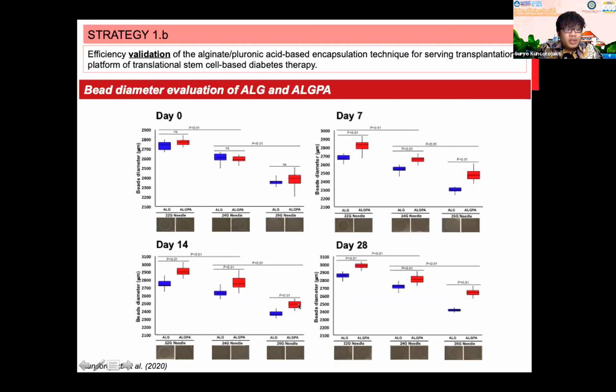The 22G needle resulted in the highest diameter in both encapsulation platforms, while the 26G resulted in the lowest diameter size. What happened with this phenomenon? Let me show in the next slide.